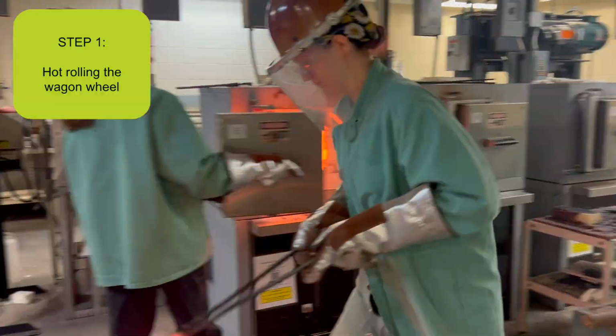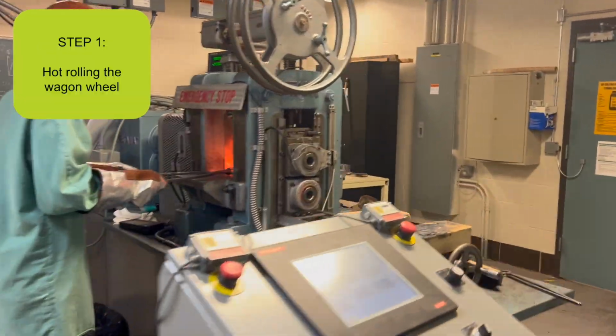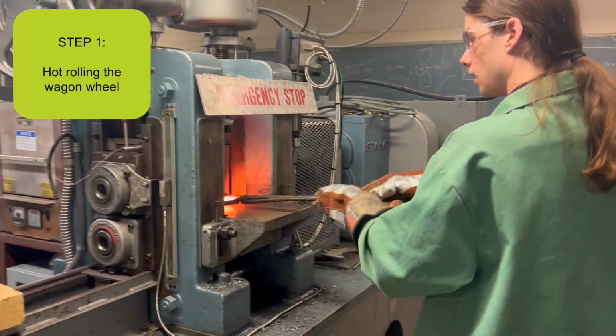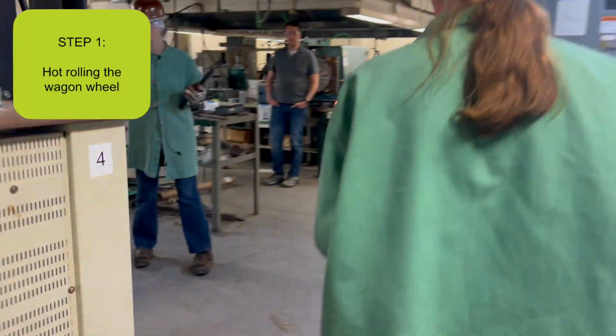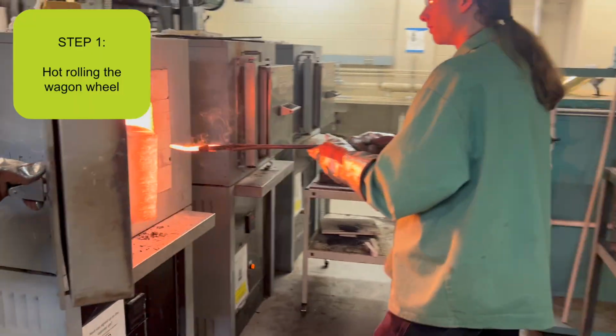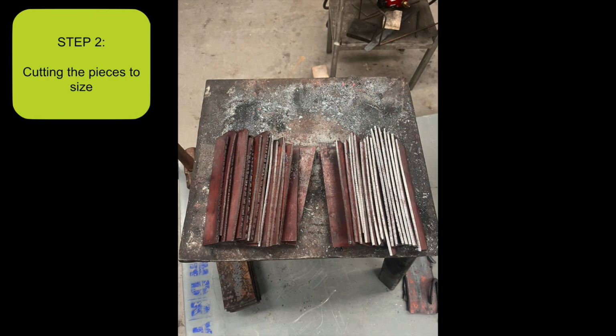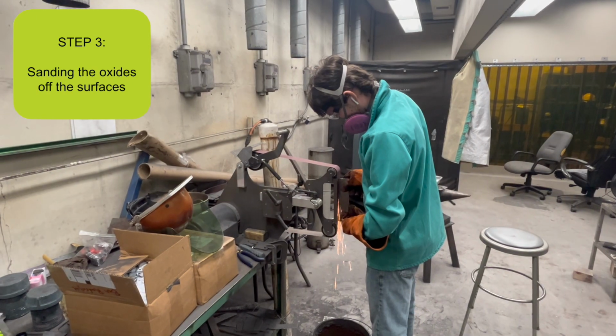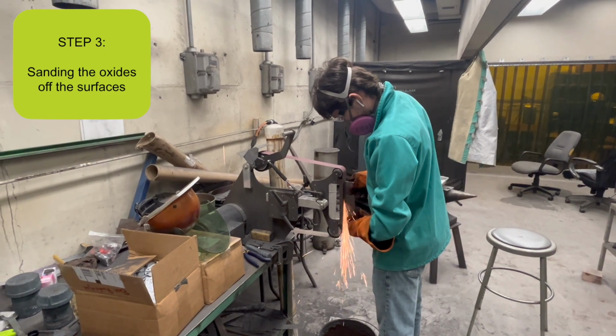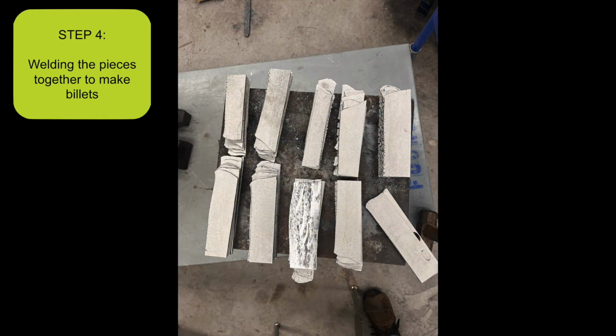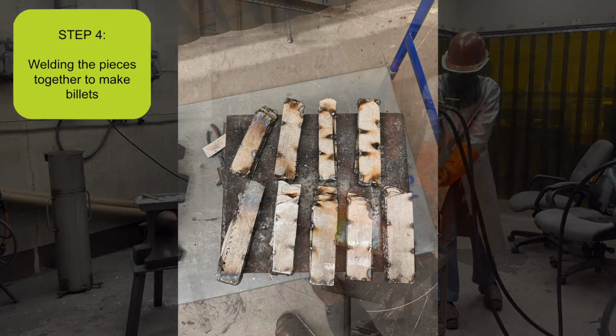The metal started its life as a wagon wheel, and our processing began with hot rolling it into manageable pieces, both to prepare the microstructure for future forging and to make sure the pieces had a uniform width. Once they were flattened, they were cut into pieces roughly the same width the final billet was supposed to be, and were sanded to remove as much oxide as possible before they were consolidated into 9 billets and welded together.